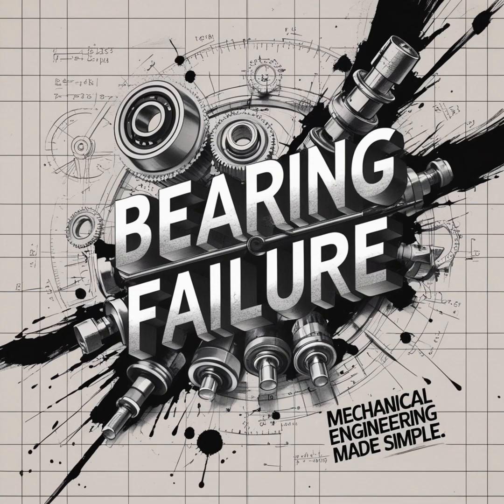These are all installation flaws. The big ones are incorrect shaft and housing fits. For example, if the interference fit is way too tight or if the housing seat itself is defective. What do you mean by defective? Well, maybe it's concave or convex or even slightly tapered when it should be perfectly cylindrical. The bearing ring gets physically deflected.